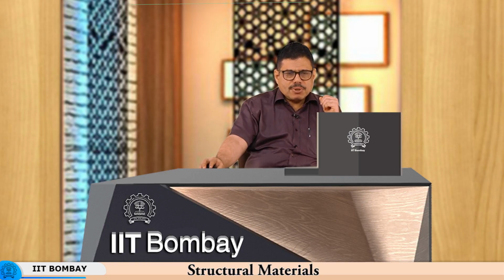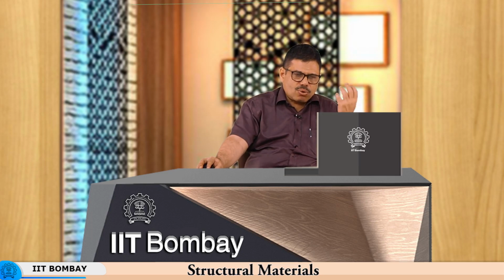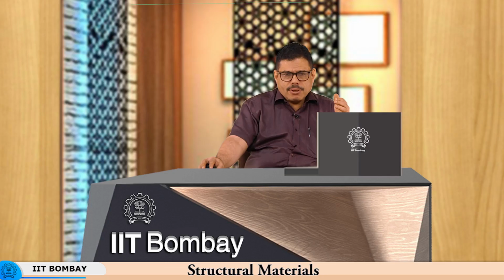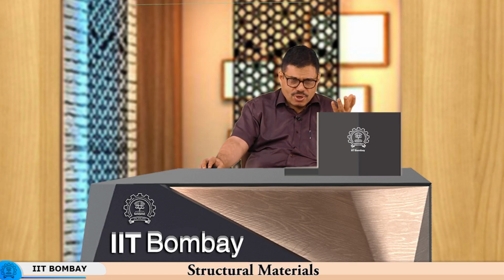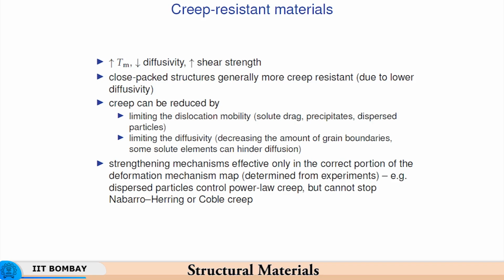Strengthening mechanisms are effective only in the correct portion of the deformation mechanism map, that is, dispersed particles would control power law creep only. They will not affect Nabarro Herring and Coble creep. So, precipitates and dispersed particles are effective in the power law creep or dislocation creep area, whereas once you have gone into the grain boundary diffusion based creep area, the mechanism of creep changes, and the creep rate will change dramatically, because the mechanisms which operated to resist creep are no longer operational. That is the reason for the dramatic change in the creep rate, as we saw earlier also, in response to a change in the mechanism of creep.